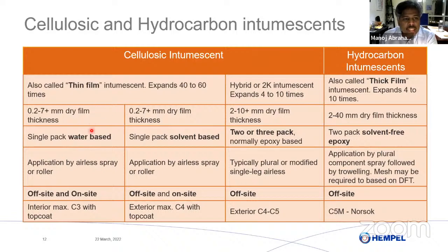Cellulosic fire protection systems can generally be either water-based or solvent-based. I will explain where a water-based coating should be used and where a solvent-based coating should be used. If you use a water-based coating system, generally the structural steel is located internally, up to a maximum of C3 environment as per ISO 12944. If you use a solvent-based intumescent coating, then we can go up to C4. So we will continue and share more details on this.